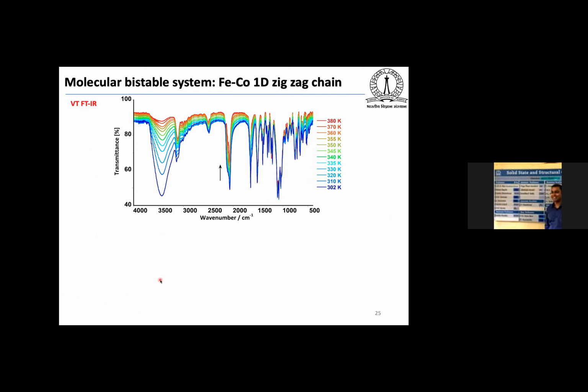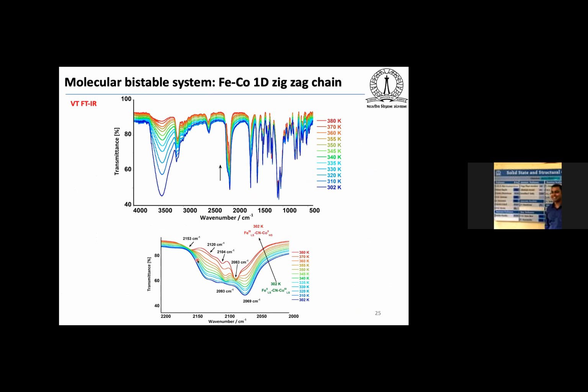And then we thought, let's check the variable temperature IR data from room temperature to high temperature, because below room temperature the system is completely diamagnetic. What we observed is that at approximately 355 Kelvin, another peak appears. I am concentrating on the cyanide bridge, because the cyanide stretching frequency will give you an interesting idea about the spin state as well as the oxidation state of the bridging metal centers. So you can see this band roughly around 2083 centimeter inverse. That is for the diamagnetic iron(II) low spin connected with a cyanide bridge to a cobalt(II) low spin center, and anything above 2115 centimeter inverse is for the iron(III) low spin, cyanide, cobalt(II) high spin systems.